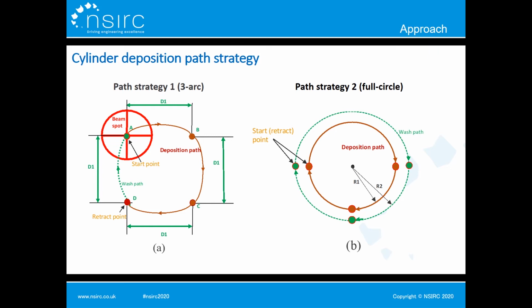After some initial trials, on the left-hand side, a 3-arc path strategy was developed. It is a similar circle route with 3 deposition paths. Because of the wire feeding angle issue, in the DA arc, the wire will get stuck in the deposition. So in this strategy, the wire will retract at point D and only laser scanning is left in the final arc to let the melting material flow to fill this gap area.